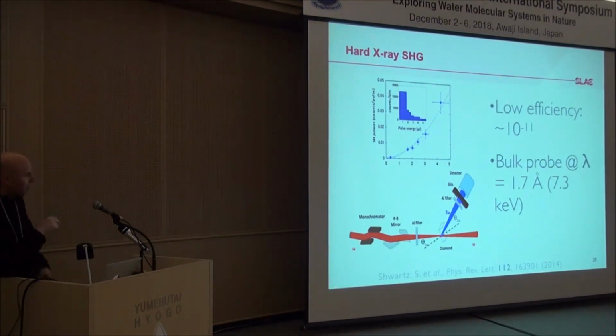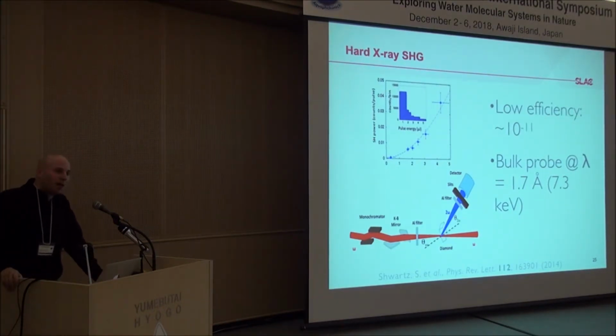And the final way to think about this is if you're a solid-state physicist, the Brillouin zone is different. One important thing that makes this technique basically hopeless to be useful is the efficiency is 10 to the minus 11. That probably doesn't mean a lot to you guys, but at an efficiency that low, you start having problems with, you're going to damage every sample.